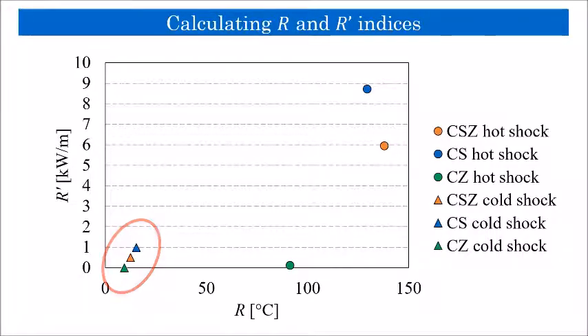As expected, all three compositions possess a superior resistance to hot shock as opposed to cold shock. Also, among the three composites, CS has superior resistance to cold shock for both mild and hard shock scenarios.